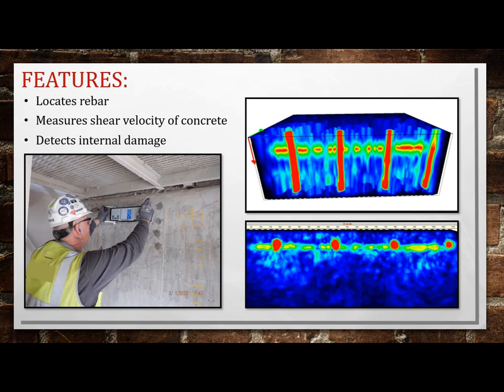And so how this differs from GPR though is this measures the shear velocity. And we said, with shear velocity, we can estimate the strength of the concrete. With GPR before, that shows you where the rebar is, but tells you nothing about strength. And also, this is good for finding defects in the concrete where radar really doesn't. So this is a good tool for detecting internal damage, measuring the shear velocity.